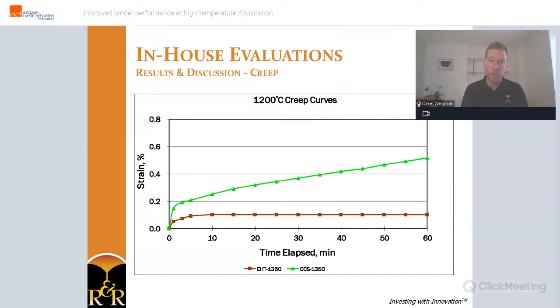And as discussed previously, shells fired at a higher temperature develop a more cohesive structure through the formation of the glass phase network. So consequently, they are more creep resistant if tested at a lower or equal temperature.